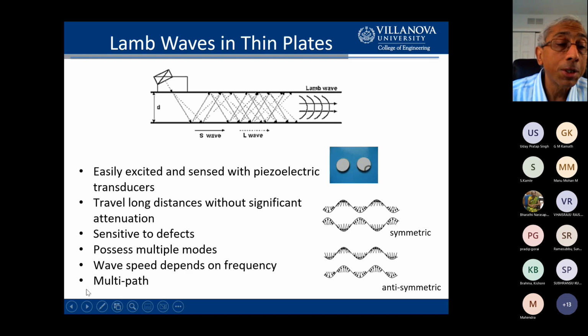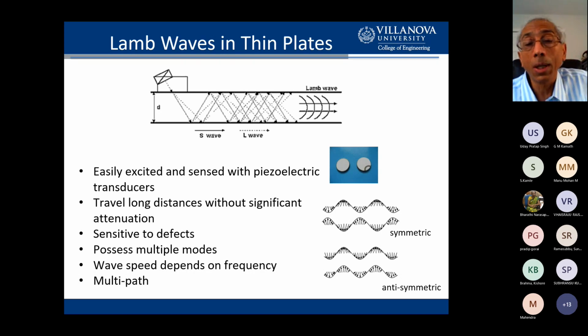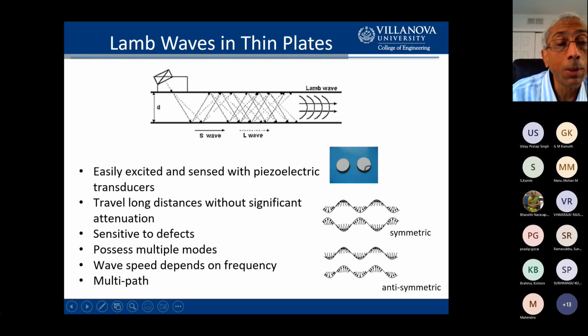And then further complications, if you have a finite size plate, then a wave that's initiated by a transducer will go out, hit the defect, and then might go hit the boundary of the plate, and then reflect back. And now you have to deal with the reflections of the boundaries of the plate too, which can, again, create a lot of confusion in your received signal. And so that's an issue too. But again, we're going to show here that we can exploit the fact that you have multiple reflections, and you can take advantage of those reflections to identify defects.